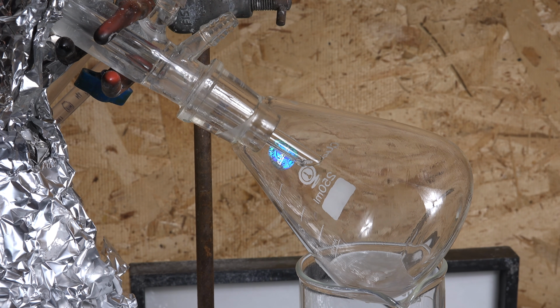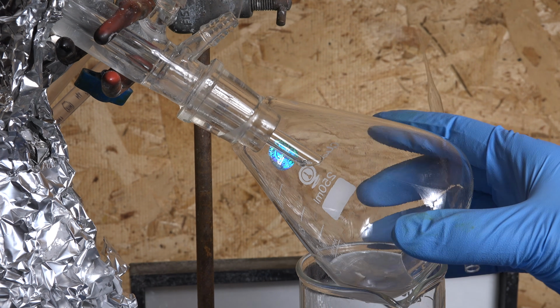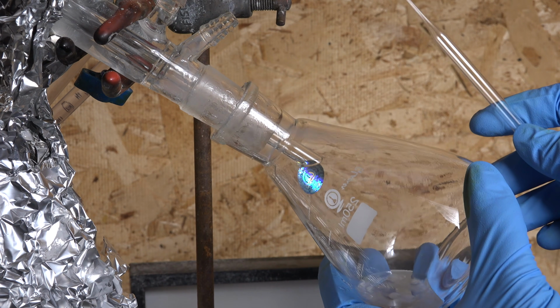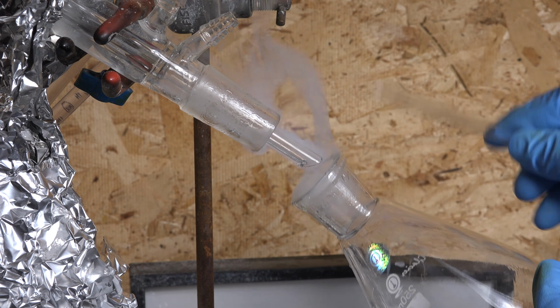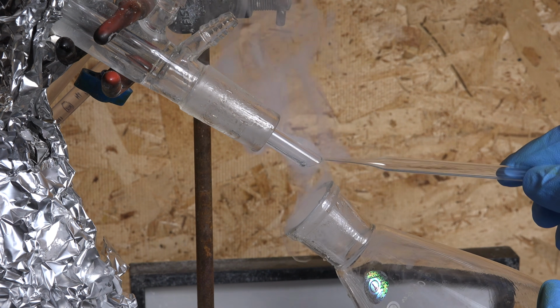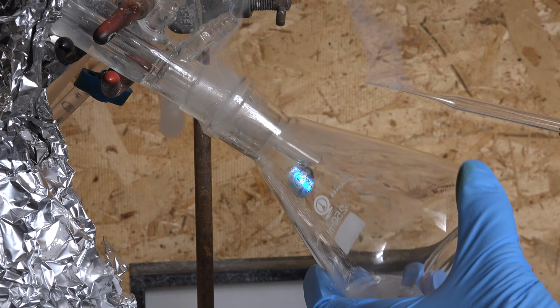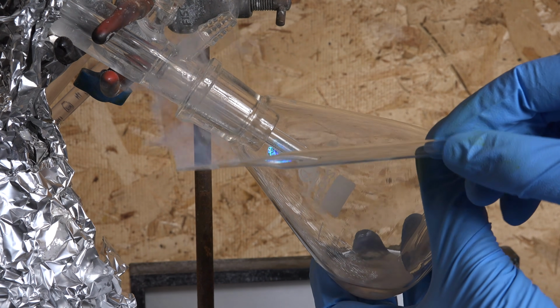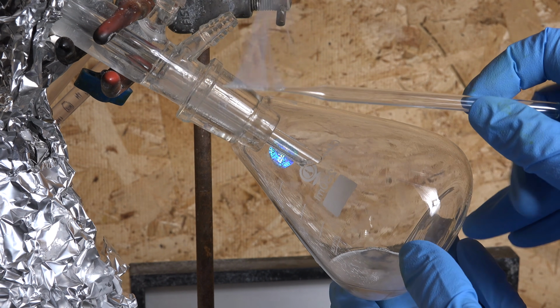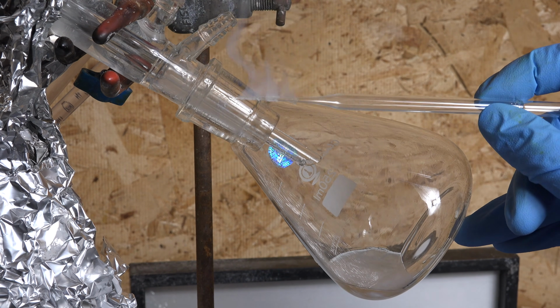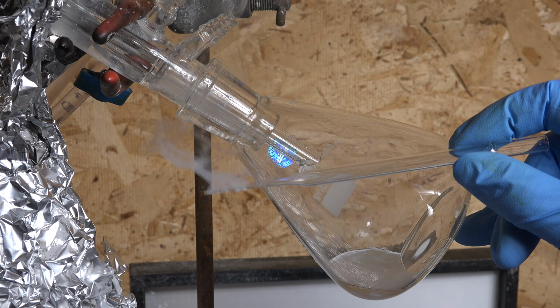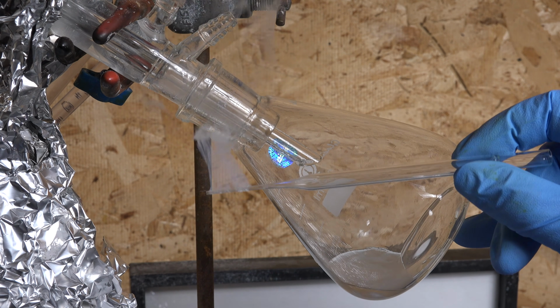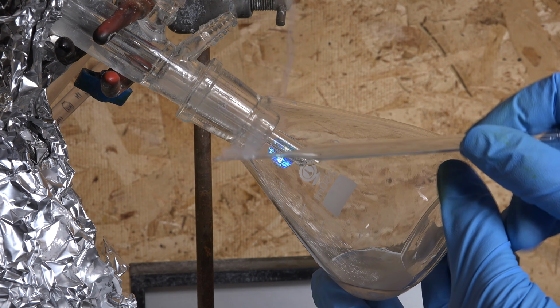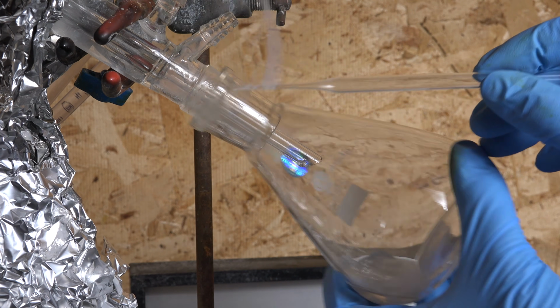So I'm going to try and force the initiation of polymerization by taking advantage of the fact that trace water will initiate it. Let me just slip off the receiver, and that massive plume of fumes is sulfur trioxide reacting with the water in the air to make sulfuric acid mist. I'm using this pipette to smear some of the dripping sulfur trioxide and expose it to the moisture of the air. The moisture alone is enough to initiate polymerization, and it might be hard to see on camera, but you can see solid sulfur trioxide is already forming on the pipette.